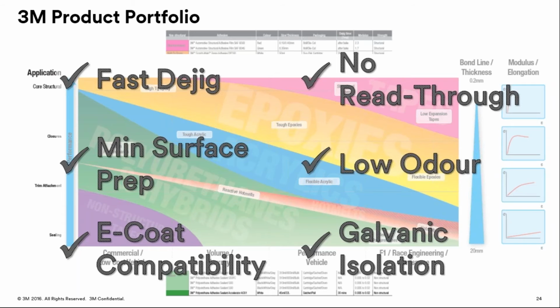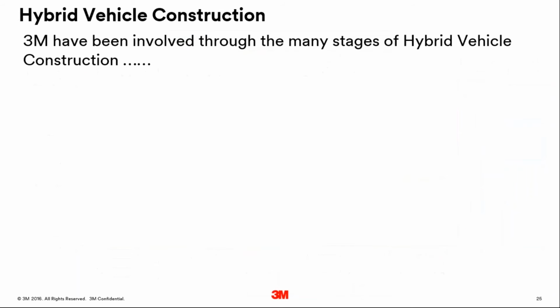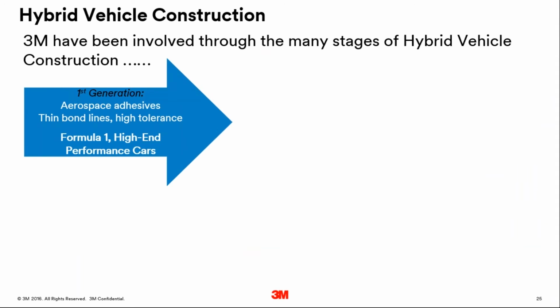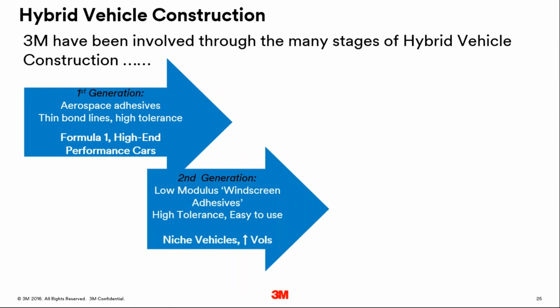Now, hybrid construction has really moved along in the last 25 years that we've been involved with it. I've called the first generation the adoption of aerospace adhesives, thin bond lines and high tolerance into things like Formula One and high-end performance cars. We then saw an evolution into much easier to use products, with some vehicle manufacturers adopting low modulus windscreen type adhesives with a high bond gap tolerance, very, very easy to use and surface tolerant. This enabled hybrid construction to be used in slightly higher volumes.